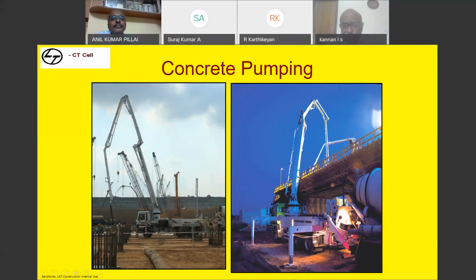Then from here, it falls with the free fall. Normally around 15 to 18 meters length, it falls in a free fall. So what you have to do is try to bring the hose as low as possible. Bend the hose at the bottom. The hose can be bent to a 90 degree, or what we can do is, here you will find a bend. This bend can be reversed.